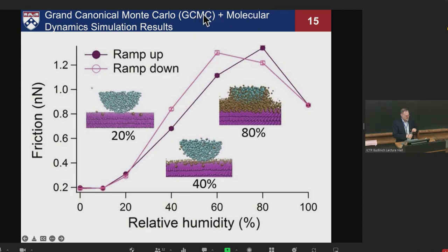Thank you. Could the water get in between the first layer and the second layer and do something else? Good question. Since we were working with graphite in the experiments, and the graphene in the simulations was large and covering the whole surface, there wasn't an easy opportunity for that. But if you had defects or edges, water can intercalate between graphene and substrates or between the different layers of graphite. So it is possible. We didn't see evidence of that, but it's something worth looking for.